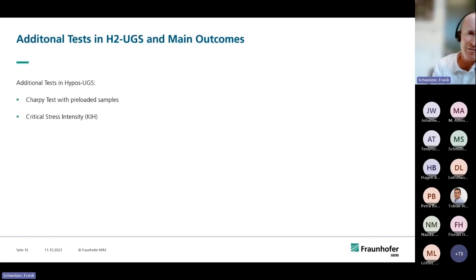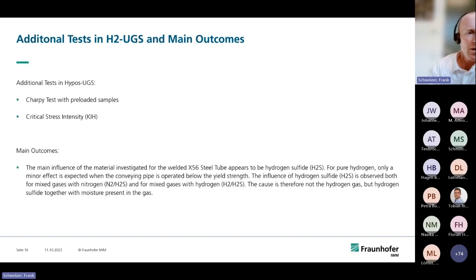And this is good for the caverns. This means you don't have a real critical stress intensity or an enhanced stress intensity with hydrogen. But you cannot really show this because if you use the standards, it's not inside of the standards. So the main outcome of the project was that for the investigated X56 steel tube, the main influence appears to be the hydrogen sulfide. So we always have to look for the H2S contents.